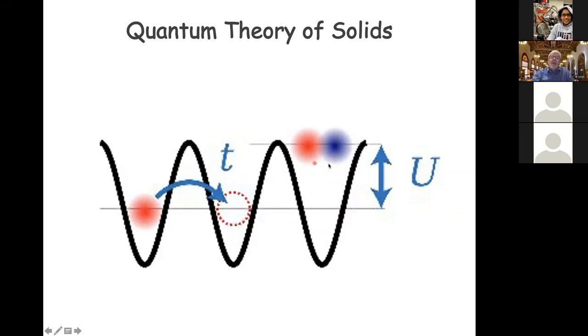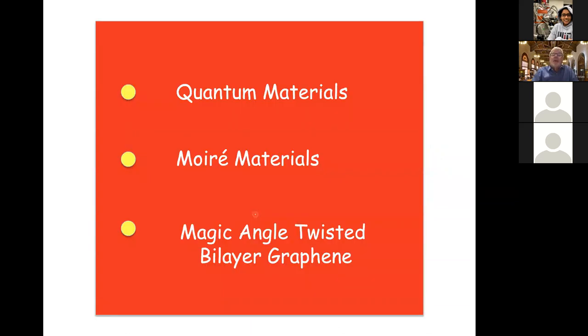And when the interaction energy scale is dominant, that means that when energy varies weakly with momentum, and therefore when electron velocities are slow, then we know from experience that, well, first of all, it's usually difficult to make any rigorous statements from theory about what the electronic properties will be like. And we know from experience that many electron states typically occur in systems in which the interaction strength is large compared to the bandwidth, so-called narrow band systems. And that's, as I will discuss, what we can generate at will in Moiré superlattices.